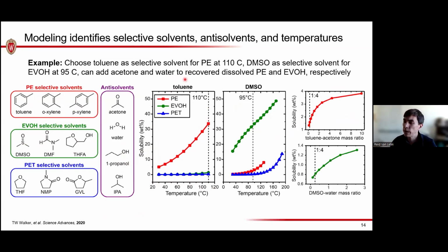So this is why toluene is a great solvent for polyethylene. I can go to a high temperature and dissolve polyethylene while not dissolving the other 2 components. So I would choose this as a selective solvent that I might use to first take off the layer of polyethylene. If I want to get the polyethylene back out of solution, I can cool it, but it'll still have some residual solubility. I can also add acetone, which is what we call an anti-solvent, and I see the solubility crashes down to a very small amount. So this is an example of how I can then trigger the precipitation, or in other words, the recovery as a solid of my dissolved material.